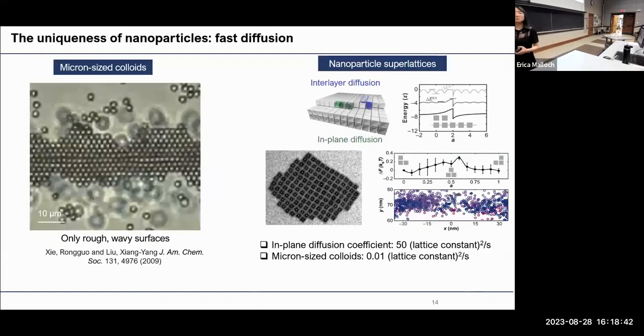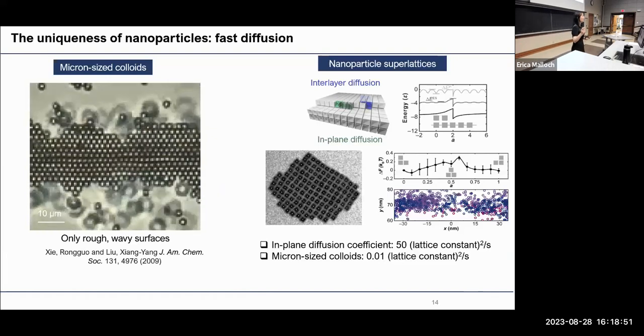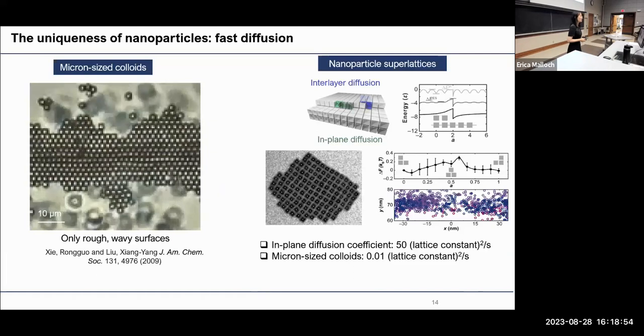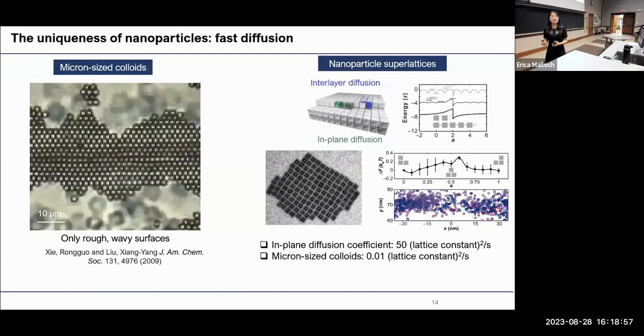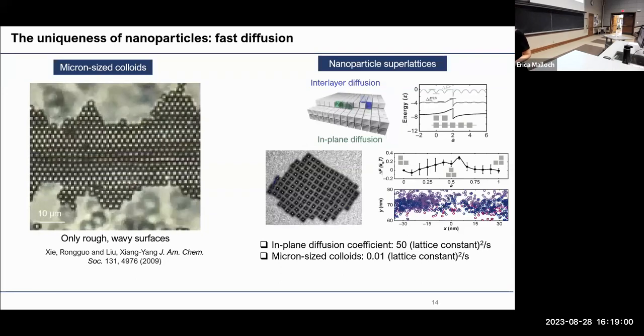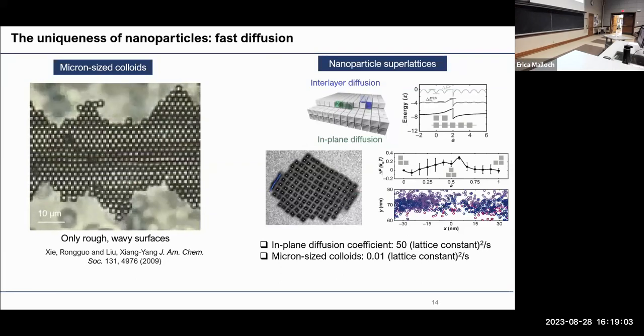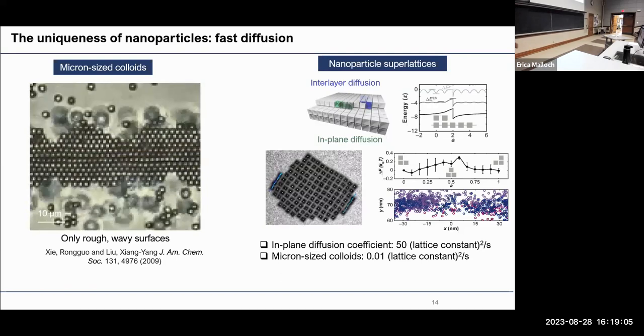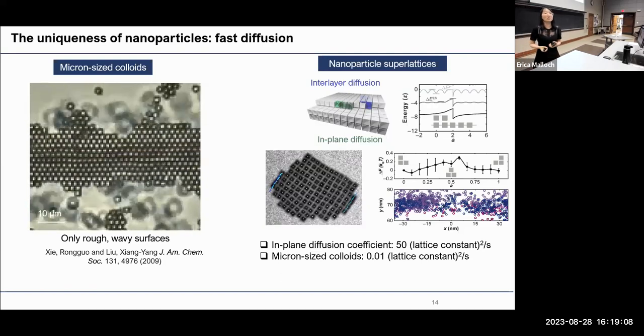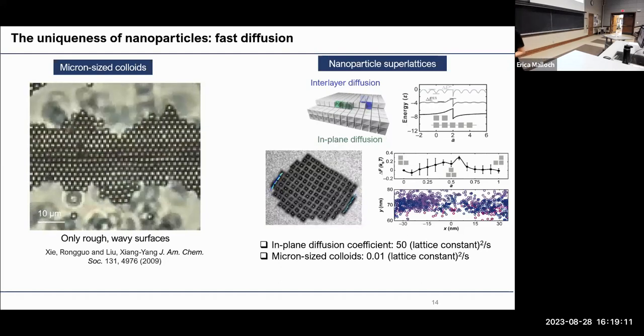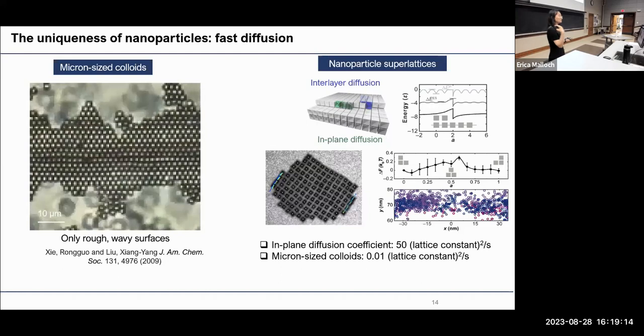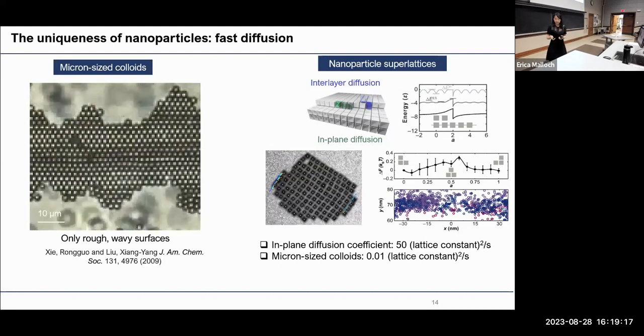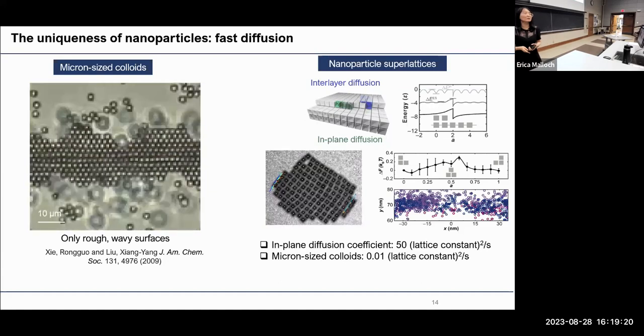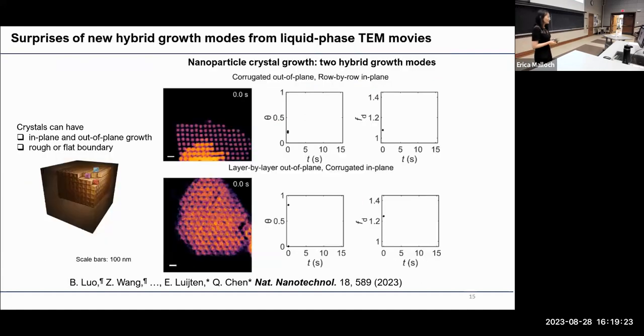If we're now dealing with much larger building blocks, the micron-sized colloidal particles, you can see the crystal becomes much rougher, as shown in this optical microscopy movie with a scale bar of 10 microns. This first hint of the dependence on building block size motivates us to realize that the diffusivity of colloidal nanoparticles, whether interlayer diffusion or in-plane diffusion, is orders of magnitude larger than that of micron-sized particles. As a result, it's very easy for them to sample all the available crystal sites. But does it mean nanoparticles will always follow layer-by-layer growth? That's not the case either.